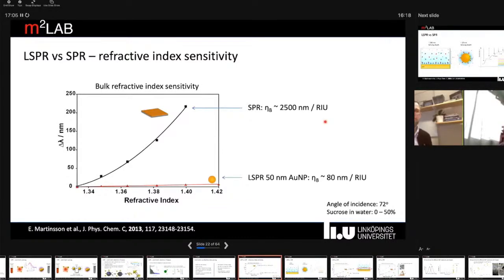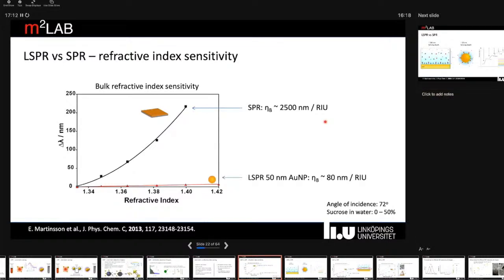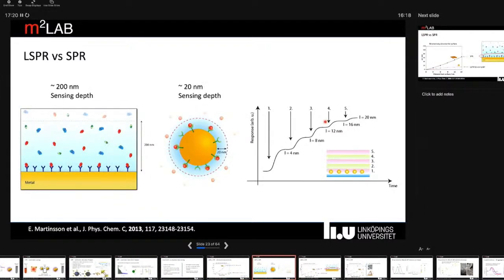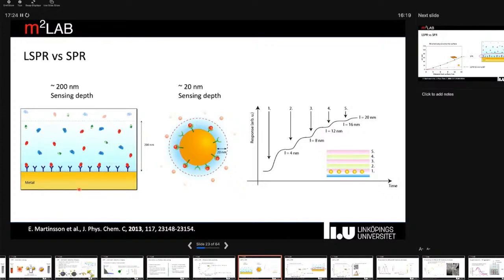If we compare the bulk refractive index sensitivity of LSPR and SPR, there is an order of magnitude difference, or orders of magnitude difference, depending on what particles we use here. And one of the main reasons for this, as I mentioned, is that in SPR we have a quite large sensing depth. So we can detect interactions occurring all the way from the surface to roughly 200 nanometers from the interface. Whereas with particles, the sensing depth is much more restricted, typically around 20 nanometers, as we can see when you adsorb polymer layers on top of the particles here, the shift decreases quite dramatically.